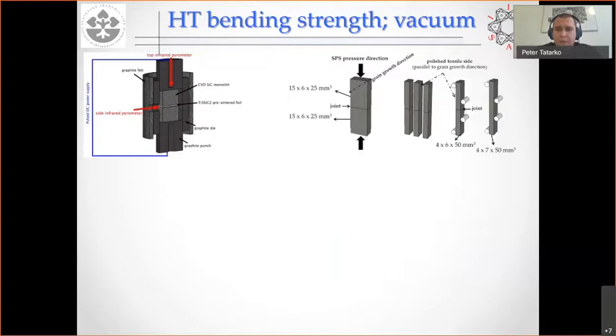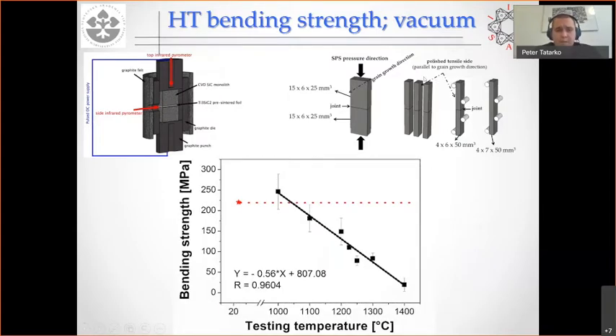We did the same preparation of the beams, and then we used high temperature bending strength testing in vacuum. When you see here, this red line shows the reference strength measured at room temperature. And then you see 1000, and then 1100, 1200, and so on. You can see that at 1000, the strength of the joint is unchanged, so temperature up to 1000 had no effect on the strength of the joint. Then the strength continuously, linearly decreased with increasing temperature.